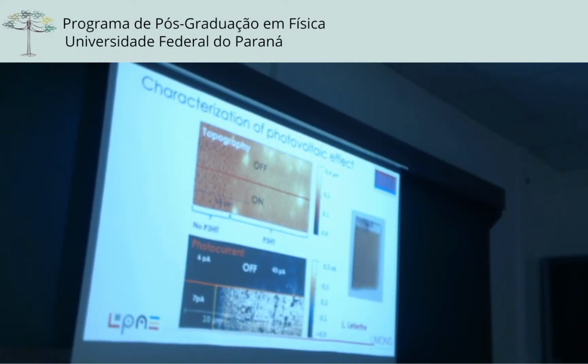If you remember the slide with the P3HT fibers and the PCBM, it was possible from adhesion to decipher the two. So once again, if you put some additives, you will see the mechanical properties changing locally, and most probably the additive is there, increasing or decreasing the properties. On paper, it's not complicated. If you have one property that you can create a contrast with, then you compare the topography and this channel, or it could also be the chemical signature with nano-infrared. If you have a region rich with this dopant, you will see the contrast between doped and non-doped.